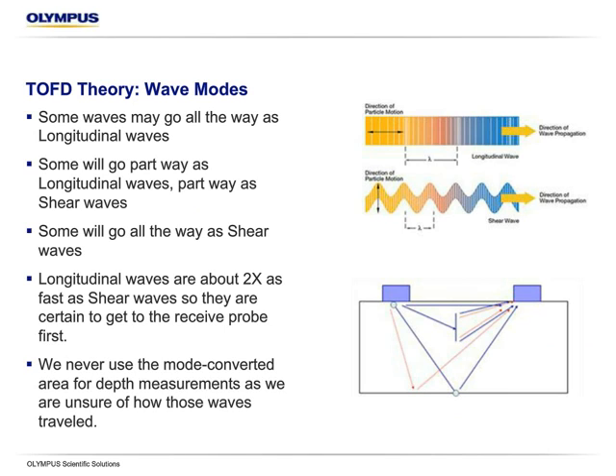So just a little bit deeper look at the wave modes. Typically in ultrasonics, there's a whole host of different wave modes that occur, but when we're doing tests for flaw detection or thickness, corrosion, we're typically dealing with two main types, longitudinal and shear wave, and it's really just how they move through the material. Down to the particle and grain levels, if we send a longitudinal wave in, it oscillates as shown on the top, sending it in a forward energy pattern, and shear wave is known to propagate in a side-to-side fashion.